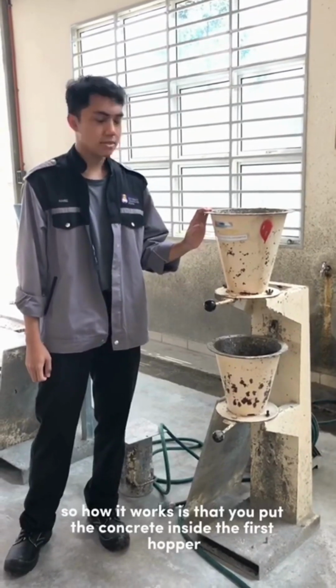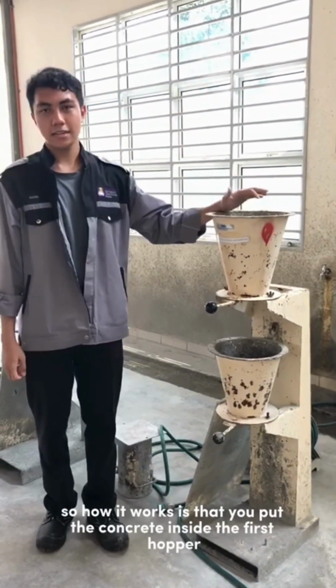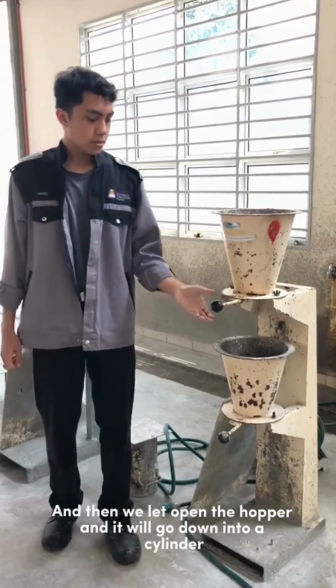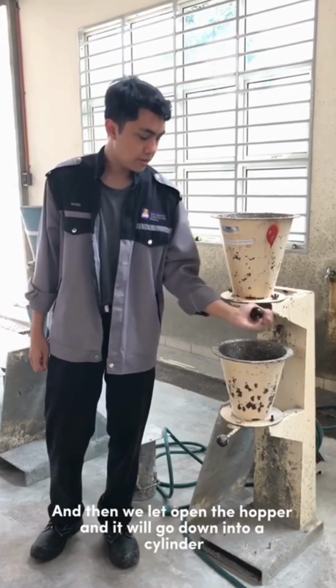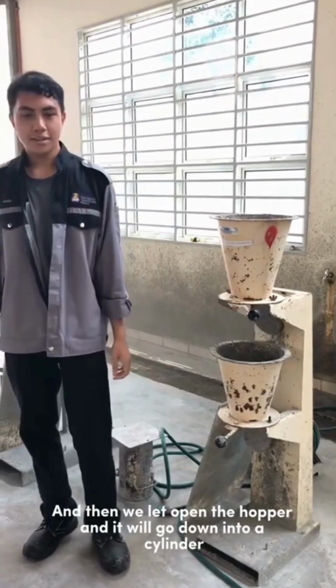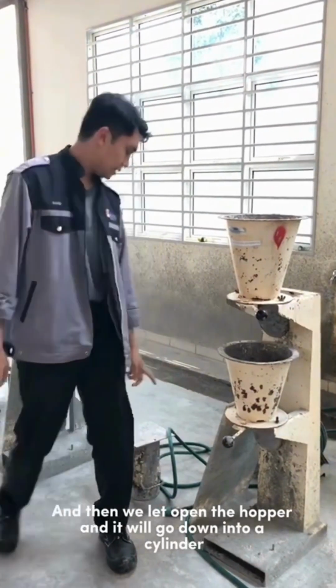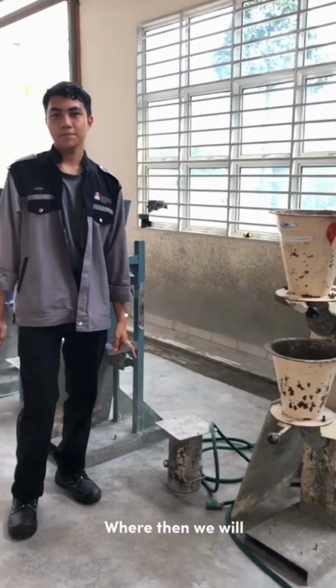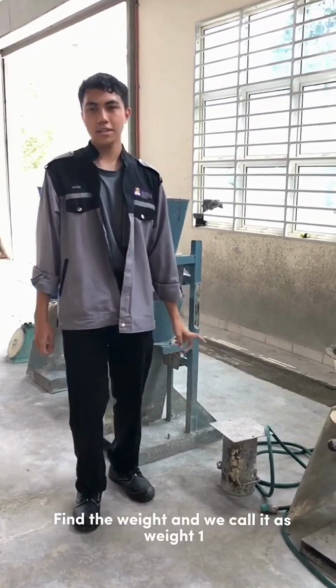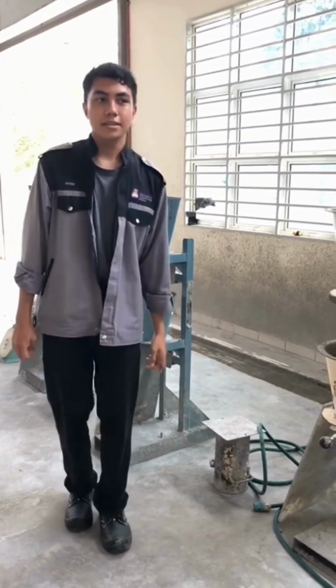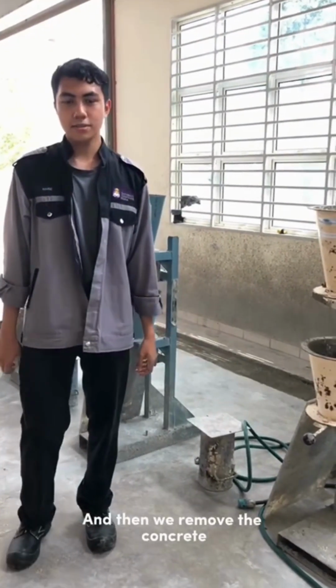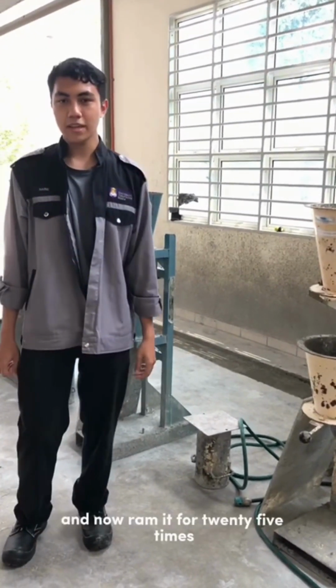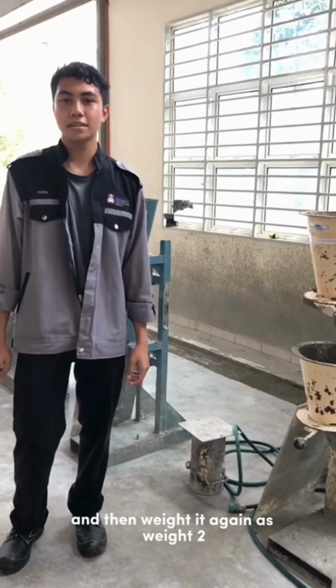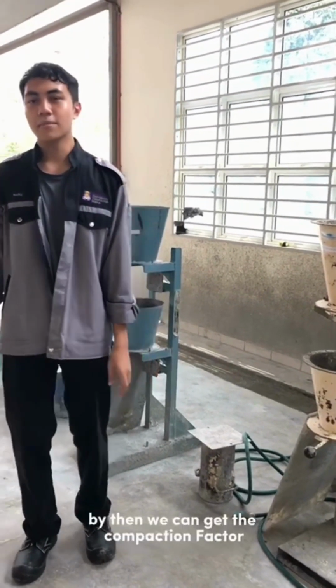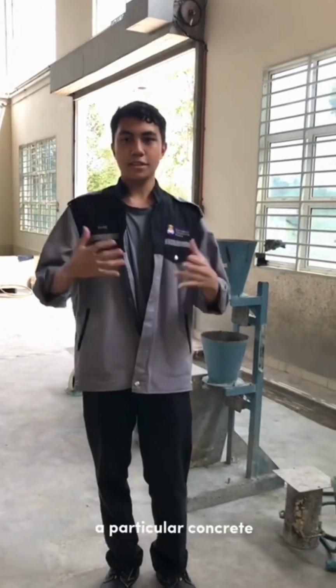How it works is that we put the concrete inside the first hopper, and then we open the hopper, and it will go down into a cylinder, where we will then find the weight, and we call it weight 1. And then we remove the concrete, refill it again, ram it 25 times, and then weigh it again as weight 2. By then we can get the compaction factor for a particular concrete.